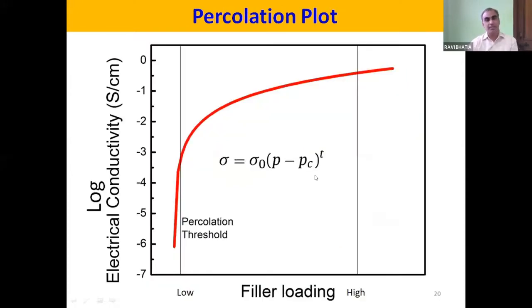So let me again explain very specifically why we are interested in these two points, where the percolation appears, and after the percolation, when you have a very high filler loading in the composite. Because at the percolation threshold, the finite room temperature conductivity is achieved, but does it sustain at low temperature or not? It is a very interesting assumption that once you have achieved percolation, that means the connectivity between the filler material should be sustained, at least in the case of carbon nanotubes, because they have quasi one-dimensional nature as their physical parameter. And after it, if you have higher loading, it should represent some Fermi gas kind of behavior.